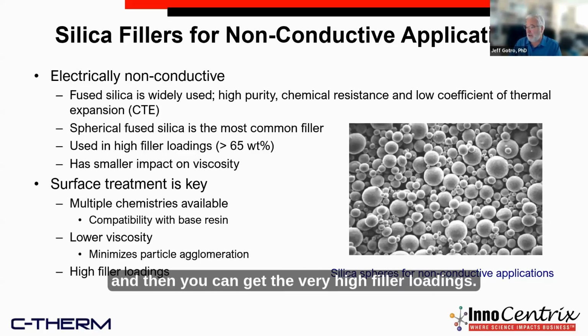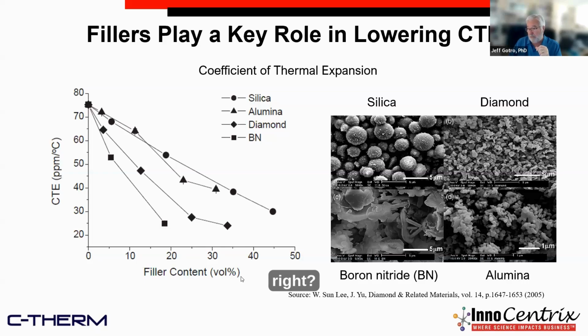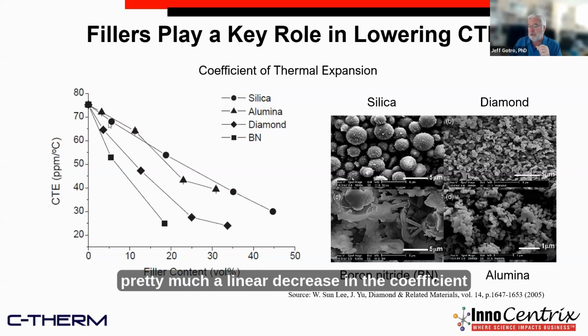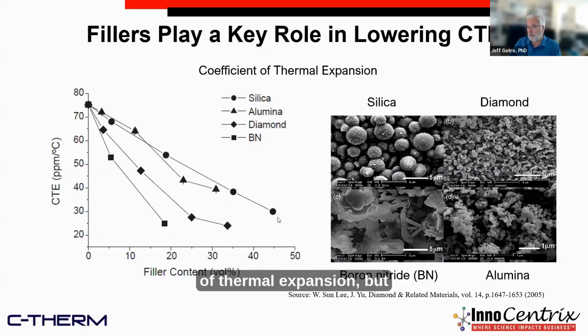And then you can get to very high filler loadings, and we'll show you how you can use bimodal, trimodal distributions to get the very high filler loadings. So one of the things that fillers are primarily used for is lowering the coefficient of thermal expansion. So on this plot, we have the coefficient of thermal expansion, and then on the x-axis here, we have the filler volume percent, right? And you can see here for silica, you can get pretty much a linear decrease in the coefficient of thermal expansion.